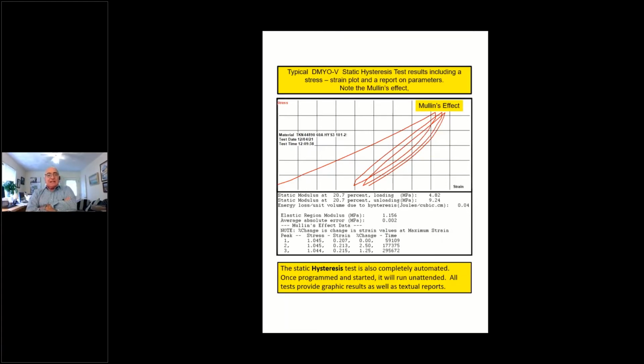Okay, this is called static hysteresis test, which really is, as we go back to the table, the moving table, we can initiate that motion. Say, between 0.1 inch and 1 inch increments, meaning the table moves and stops for a second or 5 seconds or whatever you choose. And then it takes a measurement. It carries on, moves another increment, the same increment, and takes another measurement. And that's more of a static testing. As it does that, it can do as many cycles as you want.